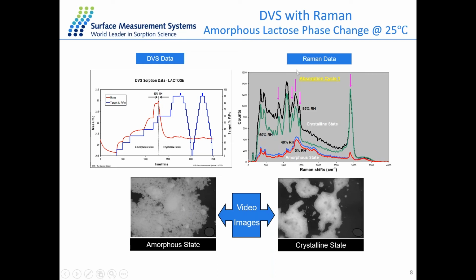And we also collected the Raman spectra at the end of each stage, and at 0 and 40% RH, this Raman spectra shows an amorphous form of the material. And exactly above 60% RH here, there are some new peaks showing up. And these new peaks indicate the crystalline state of the material. And the Raman spectra also confirm our conclusion from the DVS data that the sample goes from the amorphous phase to the crystalline phase at 60% RH.